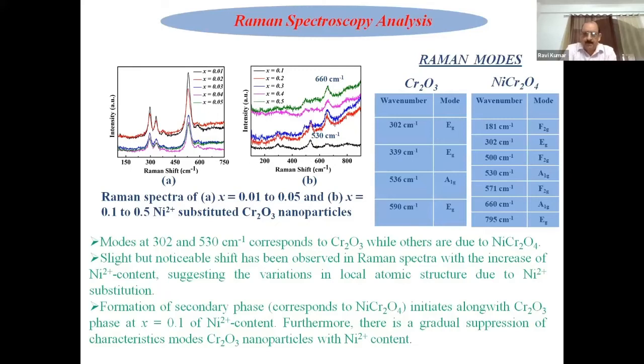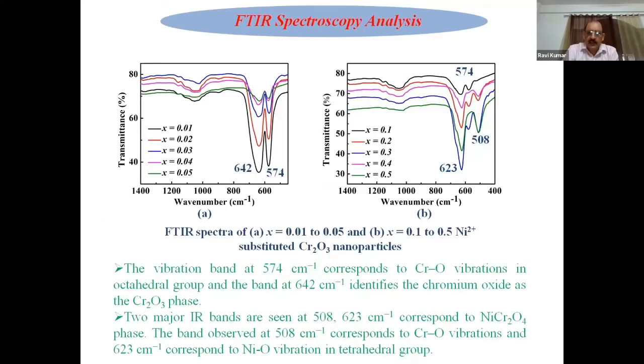Again, the Raman. So you have a low concentration part, you have a high concentration part. Here you can see the peaks of a spinel structure. Here you can see the peaks of the rhombohedral structure. Then IR also gives us the octahedral and tetrahedral structure. Here is only the octahedral structure. Here is tetrahedral and octahedral. Both are present in the system.